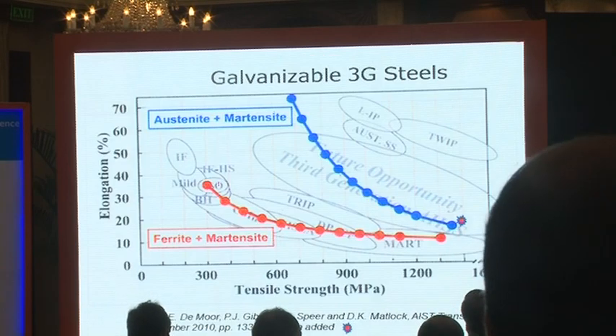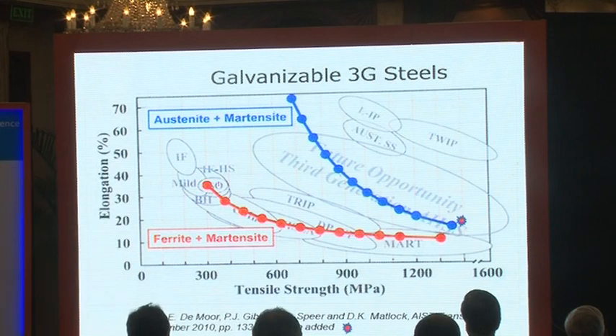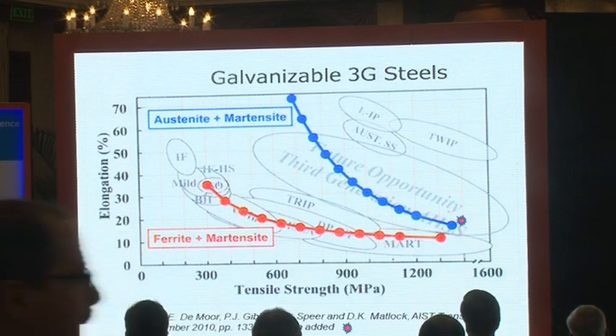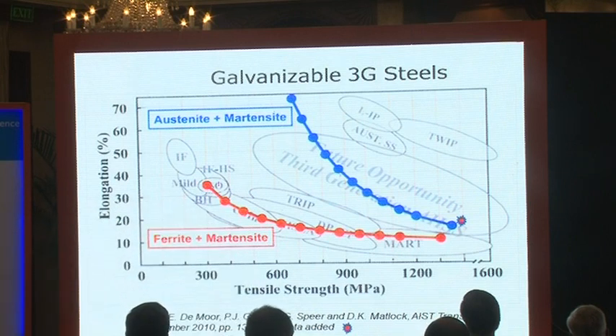So I mentioned the third generation steels. This is the austenite martensite line, this blue dotted line as we see on the top line. And the 2 points we have already in the GAP program are indicated with the stars over here. These are where our steels are sitting, so we're way off the curve up here, but if we temper back, we can get it back in this range here.